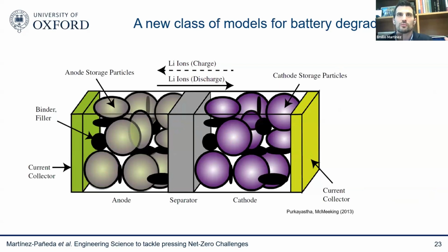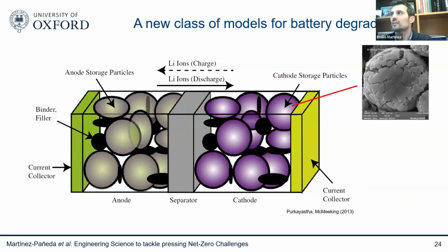And every time you charge and discharge your battery, you swell and shrink your particles, and that leads to the initiation of cracks, as you can see in this microscope image. And this is the reason why we need to change our laptops, our phones every 2-3 years, because the battery is degrading, because we have these cracks appearing as a result of this charge and discharge, these lithium atoms going in and out of those particles.